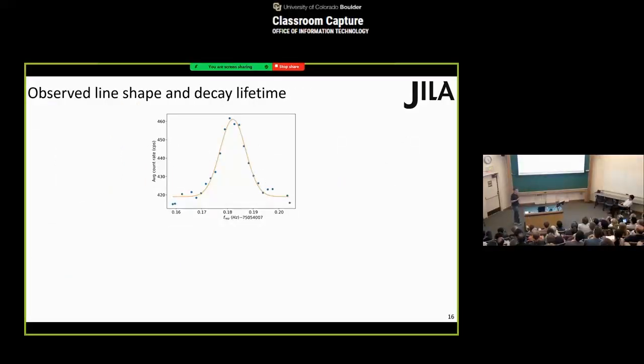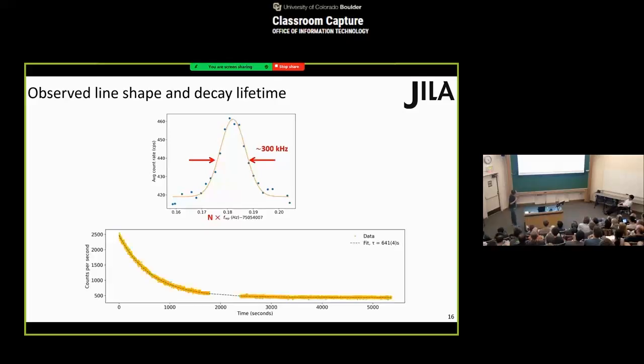Now we can zoom in to one of the transition lines and study the transition line shape. Again, the horizontal axis here is the comb repetition rate. But if we multiply by this large number n and go back to the optical transition frequency domain, the transition linewidth is about 300 kilohertz. We think this is still limited by the linewidth of our VUV frequency comb, and we have some ideas on improving that further. If we look at the time domain decay of this fluorescence, we can see that it follows a single exponential decay very well, with a very long lifetime of about 641 seconds.